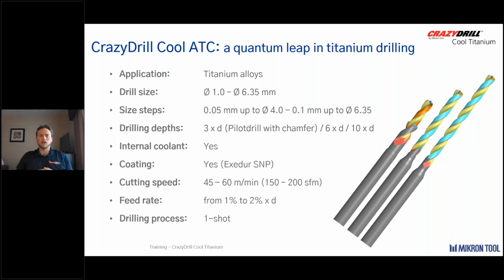If we're dealing with extraneous circumstances where, for whatever reason, we can't break a chip, we have run those systems with success. But for the ATC and alloy titanium, this drill was designed to make small chips consistently to depth in one shot. If we add a PECK cycle in, we're adding a lot more wear and tear to the amount of contacts we're having with the tool, and I would expect to see decreased tool life due to the increased wear, particularly at the point and the corners of this tool.